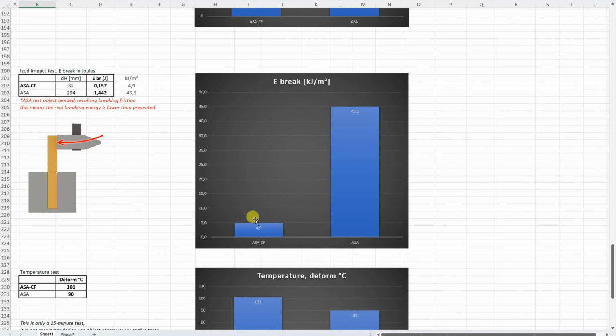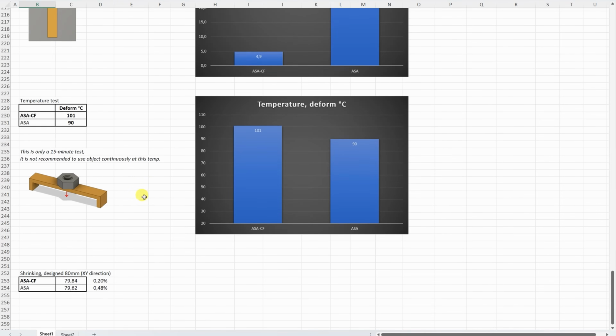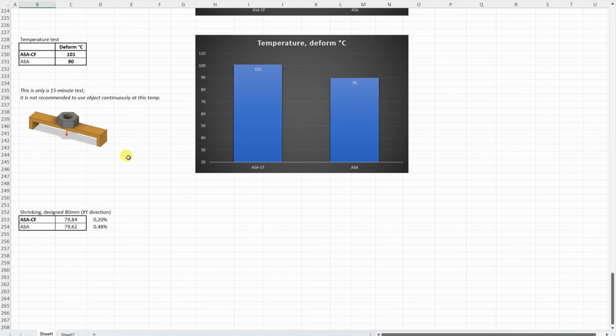And on the Izod impact test, huge difference here. So the regular ASA is a very tough material, and the carbon fiber version is very brittle compared to this one. On the temperature test, no surprises here. Those carbon fibers always help here, and it was slightly better compared to the regular ASA. And maybe interesting data is the shrinking, and this is again typical for these carbon fiber filaments, that they have better dimensional accuracy, less shrinking.